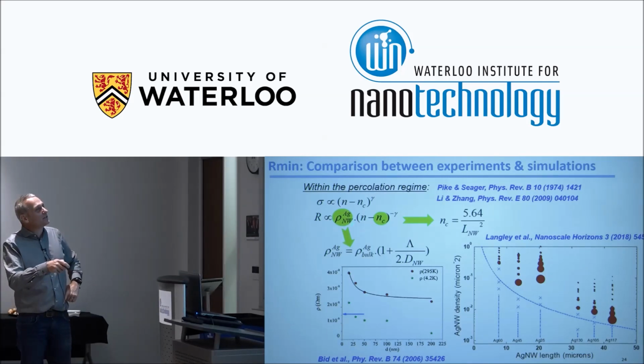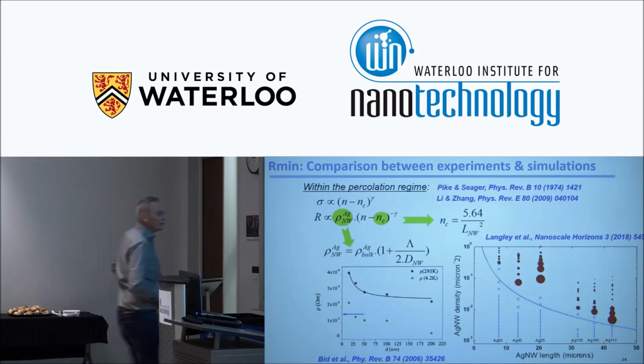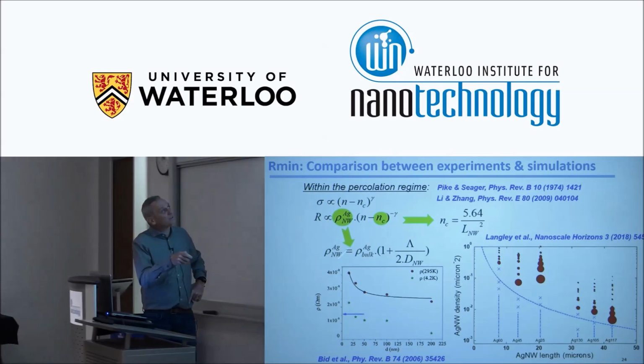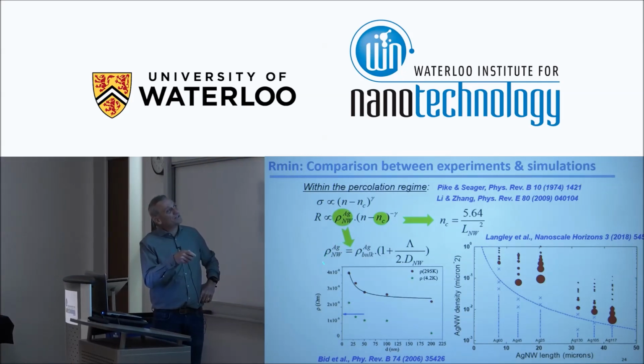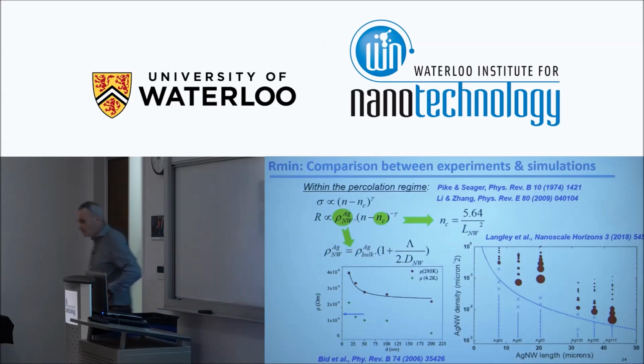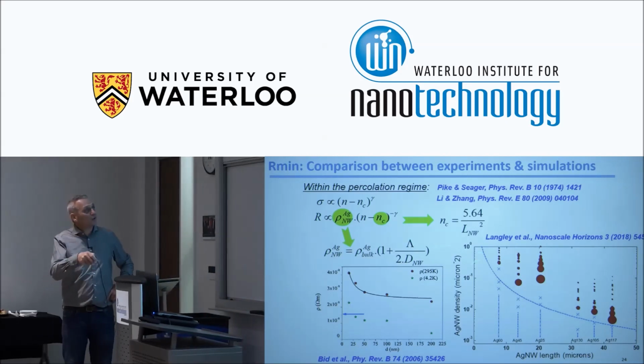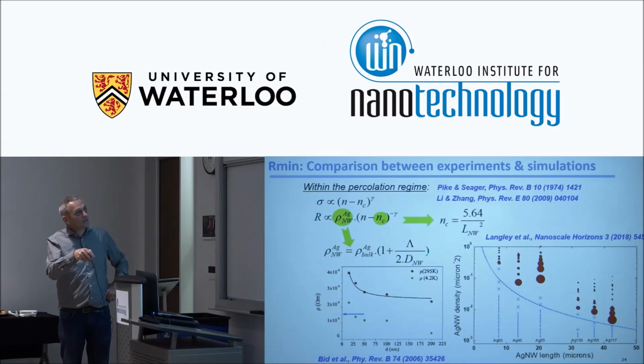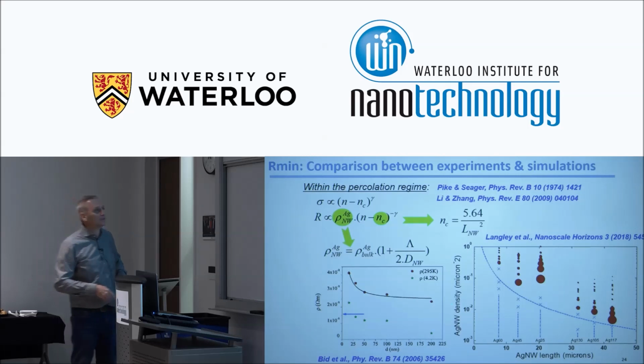And here as well, there is an influence of the diameters. There was a nice paper by Bid et al. in Physical Review 12 years ago, and they showed experimentally and theoretically that the electrical resistance of the nanowires is the one from the bulk times 1 plus the mean free path of electrons, which is about 50 nanometers in bulk silver, divided by 2 times the diameter. And they observed that when the diameter is lower and lower, the electrical resistance of the nanowires is increasing. Okay? And quite a lot, it could be a factor of 2, something like this, especially for small diameters.